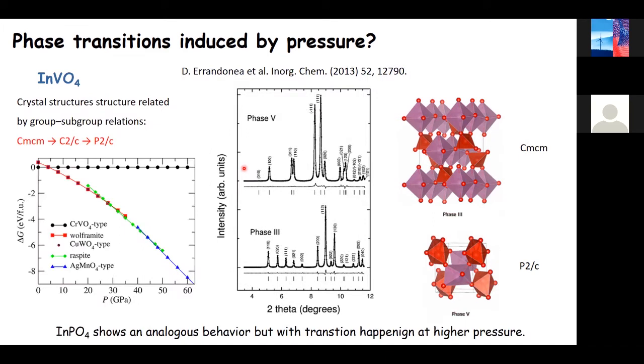So more things. Our colleague has done ab initio calculations. This is the enthalpy, the free energy, versus pressure. And you can see that at low pressure, the most stable structure is this orthorhombic one, which is the expected one. But as we increase pressure, the monoclinic structure, which is this one, becomes the more stable. It's the so-called wolframite structure here. At pressures beyond the limit of our studies, our colleague predicts two additional phase transitions, but I will not comment on that here. This is beyond the scope of this talk.